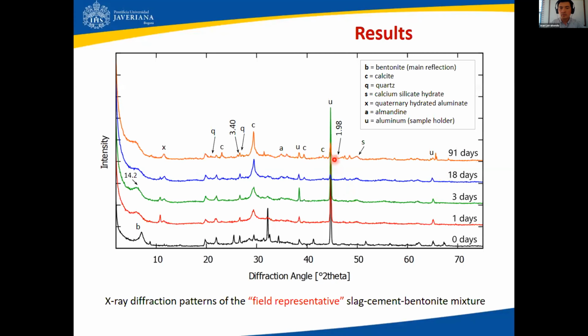For now, what I want you to look at first is the U peak. I labeled it U for the lack of other letter to use here. That is an artifact of the testing, which is aluminum, because the sample holders that held the actual samples were made of this metal. So this peak is, of course, very sharp and very high, but it's not significant for this study.